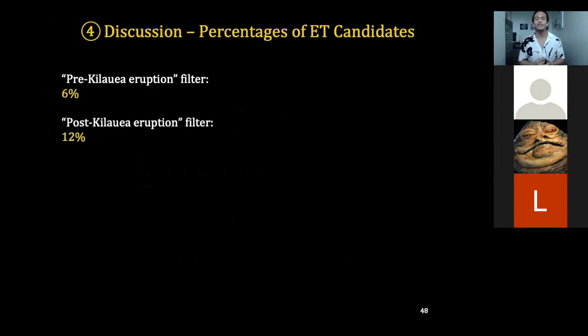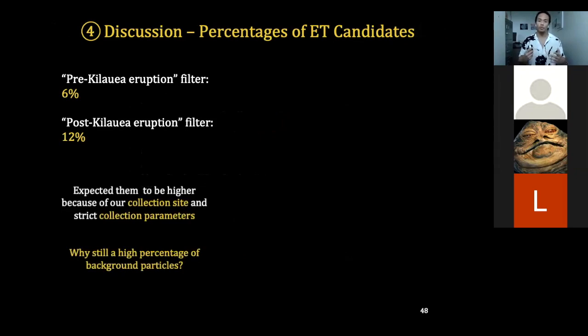Circling back to the percentages of the ET candidates that we got, again, for the pre-Kilauea eruption filter, as I mentioned before, we got 6%. For the post-Kilauea eruption filter, we got 12%. These were actually lower than what we were hoping for, simply because, as I mentioned before, our collection site was in an isolated region, and then we employed really strict collection parameters. So why is there still a high percentage of background particles?